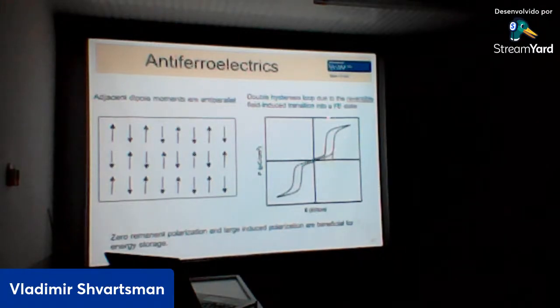A typical feature of an antiferroelectric is the so-called double hysteresis loop. What it means is that we start from this anti-polar configuration, which has low dielectric permittivity and low polarization, and we apply the electric field. Above some critical electric field, we switch the dipole moment of one sublattice along the field. So we induce the transition from the antiferroelectric state to the ferroelectric state, and this is accompanied by a jump of the polarization. Then when we decrease the field, since this induced ferroelectric state is actually metastable, or thermodynamically unstable, below another critical field, which is lower than the first one, we have a transition back to the antiferroelectric state. So zero remanent polarization, small dielectric permittivity at low fields, and large induced polarization are good for energy storage.